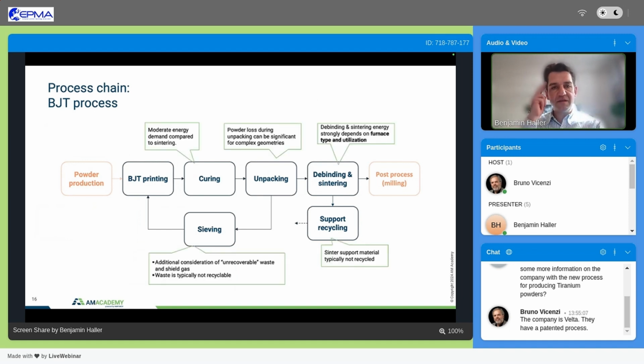Then looking at the binder jetting process, one of the most important factors is actually the debinding and the sintering. What is the case very often for the binder jetting process is that a small, rather inefficient sintering oven is being used. So this will have a very strong impact, both the utilization of this furnace, but then also how much energy is lost during the sintering, and how much energy is used to basically reintroduce into the process.